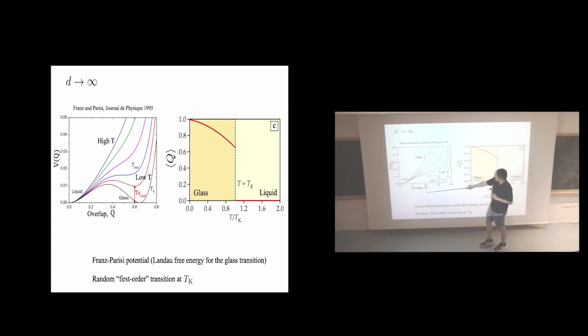So at high temperature, we have a single minimum here. And this minimum corresponds to the liquid state, so zero overlap, okay? But with decreasing temperature, we start to see a second minimum here. And this second minimum corresponds to the glass state, but still a metastable state with respect to the liquid. Then if you decrease the temperature further, at a certain temperature, precisely TK, this minimum touches the x-axis. So this corresponds to the ideal glass transition.